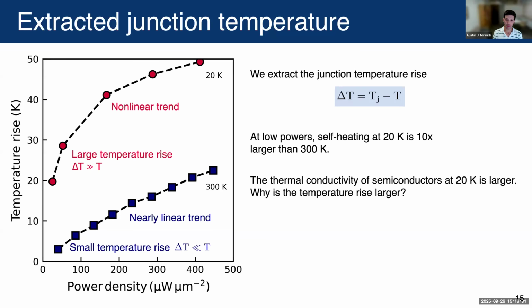Now, in the field, this was not expected because if you look up the thermal conductivities of the various materials, typically the thermal conductivity of semiconductors is 10 times bigger at cryogenic conditions compared to room temperature. So it was kind of assumed in the field that self-heating would be negligible at cryogenic temperatures. But clearly the data is telling us that it's very important. And in fact, it's the dominant effect.